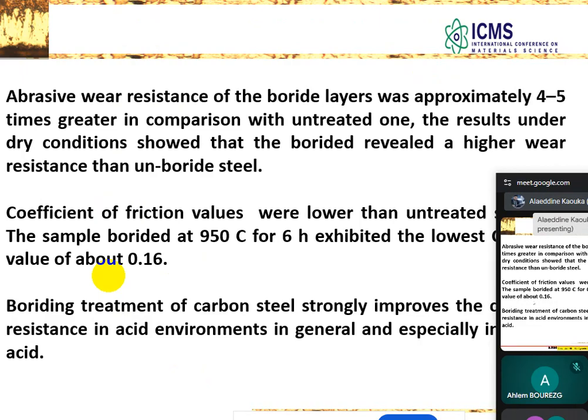So I will conclude that the new technology was used to evaluate the boride layer thickness for titanium alloy successfully. It showed the sawtooth structure with a depth of about 200 micrometers, and the micro hardness was between about 1170 and 1870 HV, and the fracture toughness ranged between 3.9 and 4.48. And the activation energy, sorry, I didn't give details about this. Activation energy is about 260 kilojoules per mole.